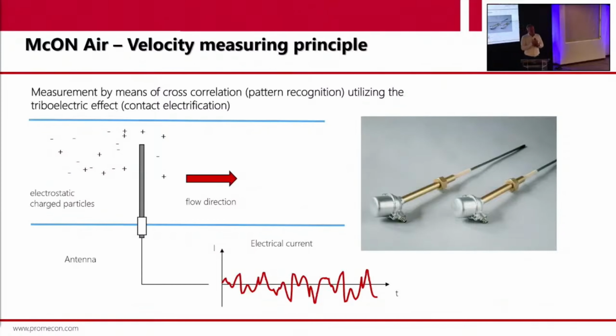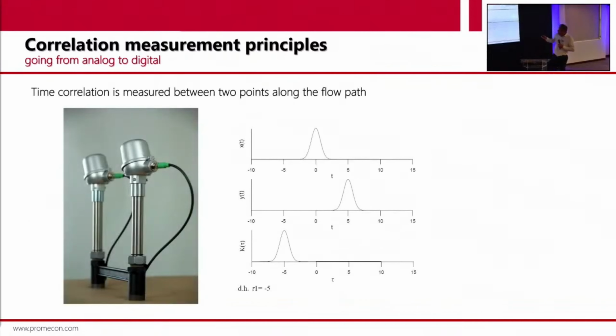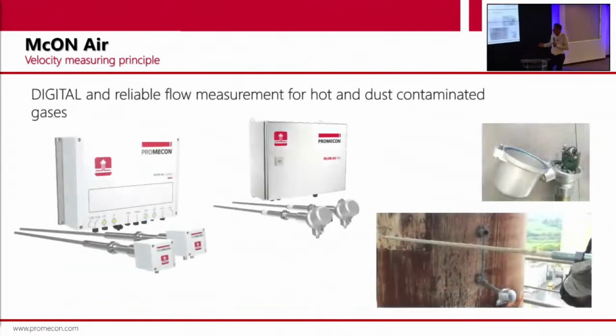So the clouds leave a characteristic signal on your sensor, and that is important because the characteristic signal contains information, right? What information is that? We basically take two sensors in series, sensor 1, sensor 2. If you put them close, like 300 millimeters, then the time signature in a certain time on both sensors will be very similar. The flow pattern does not change within 300 millimeters, right? Let me show you that.